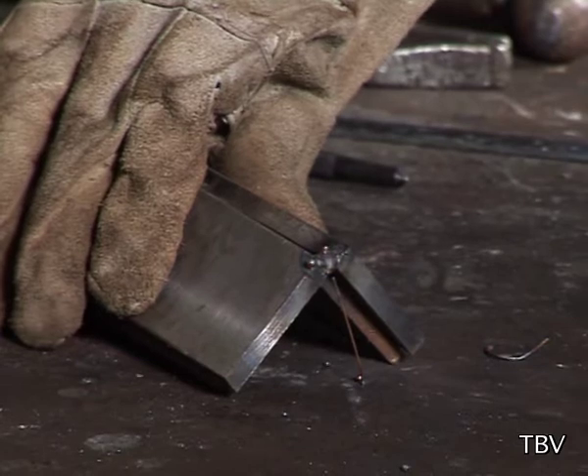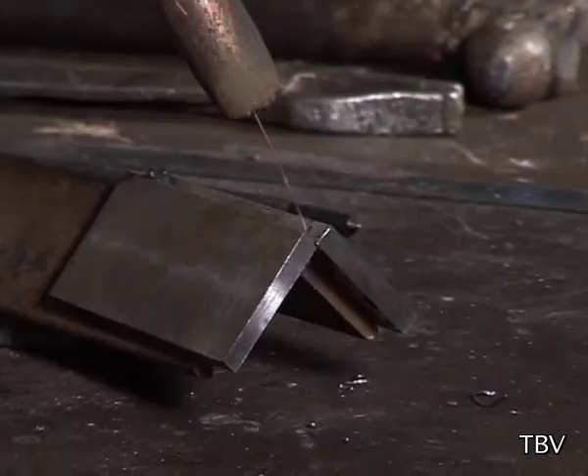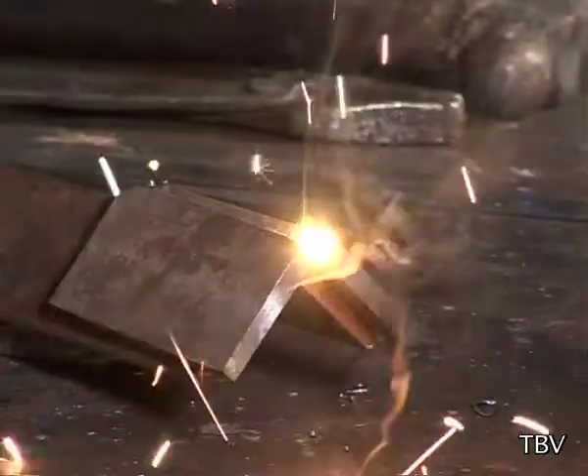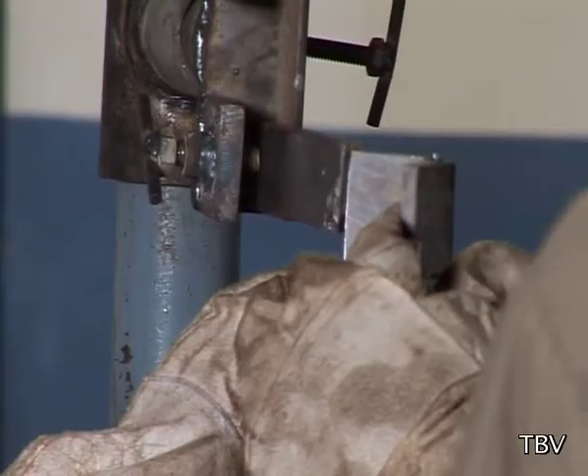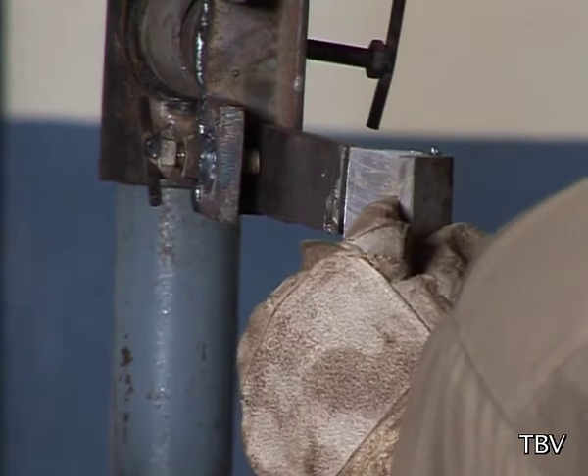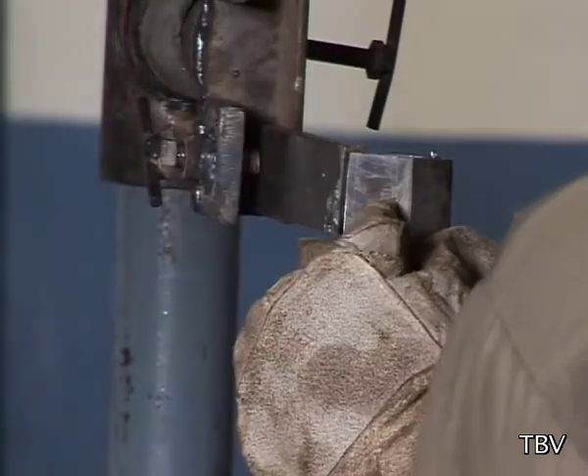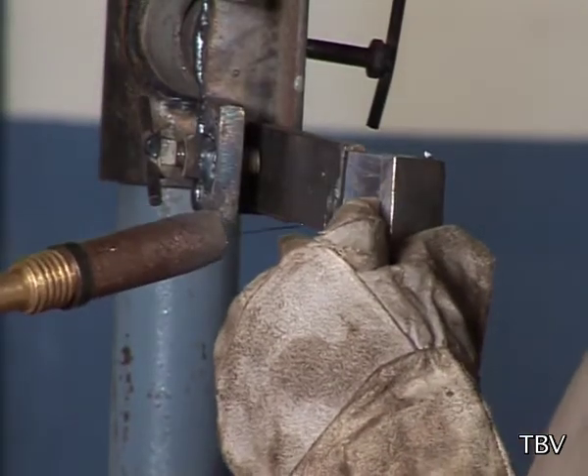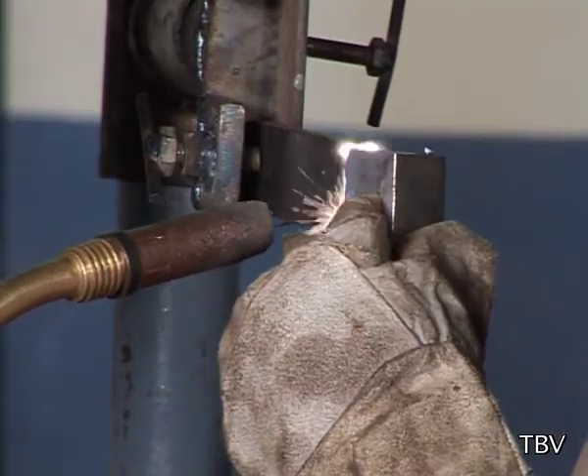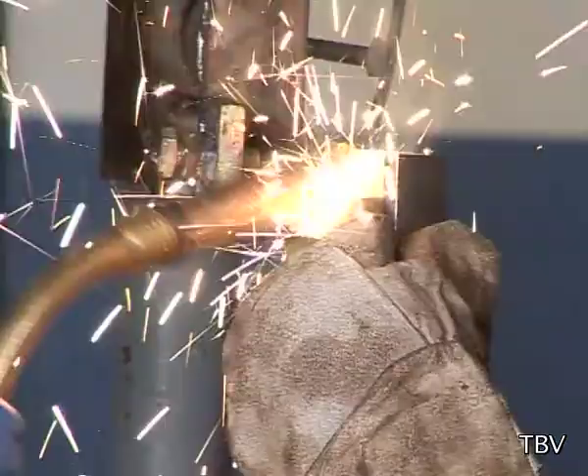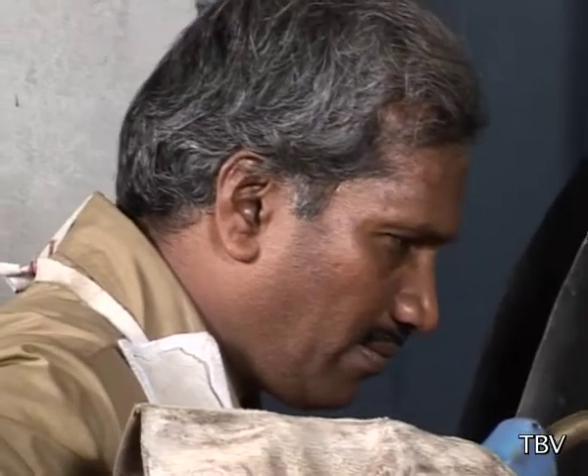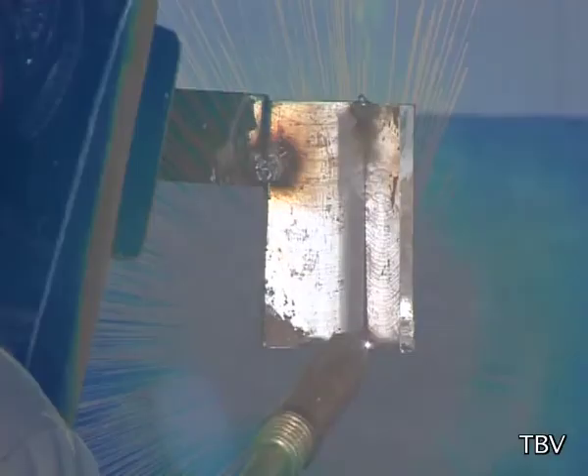Tack weld the job. Mount the job such that the plate is vertical and the scribed lines are in horizontal position using the job positioner. Hold the gun perpendicular to the joint and strike the arc at the tack. Move the torch from bottom to top end of the joint in vertical position.